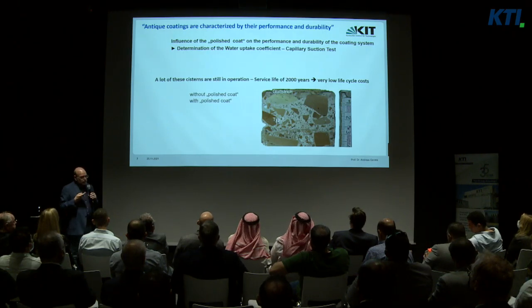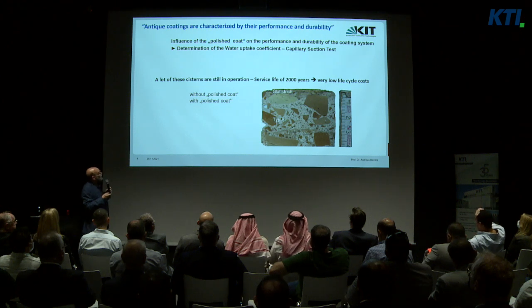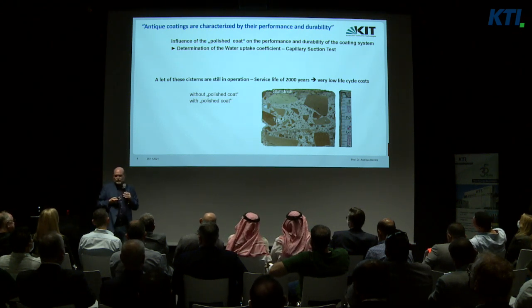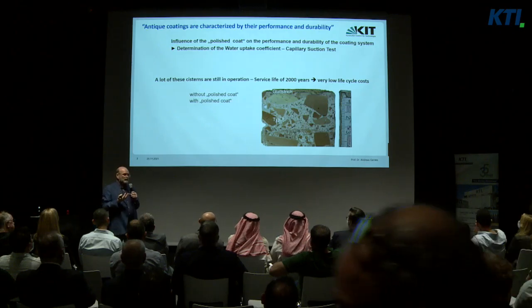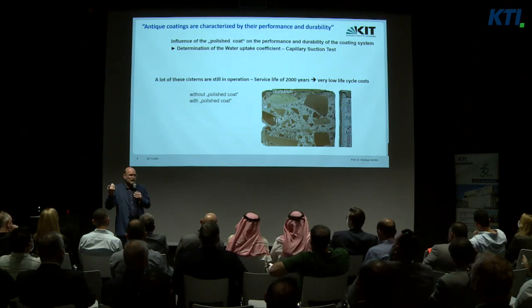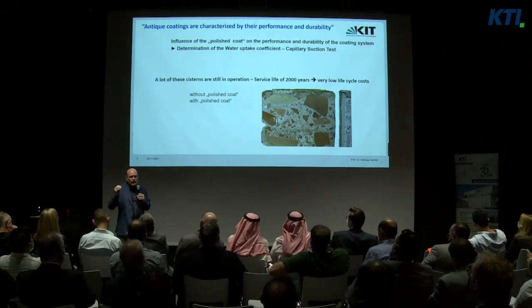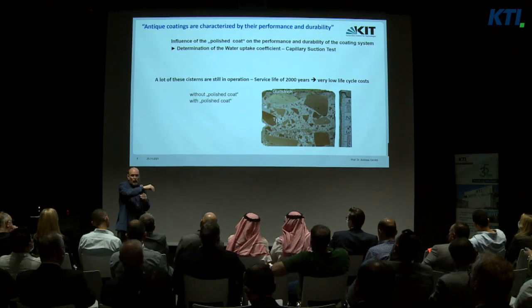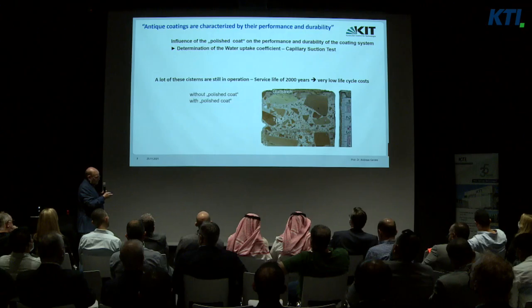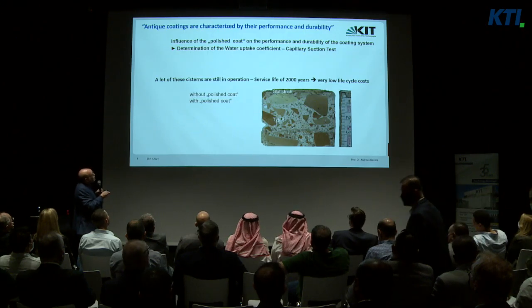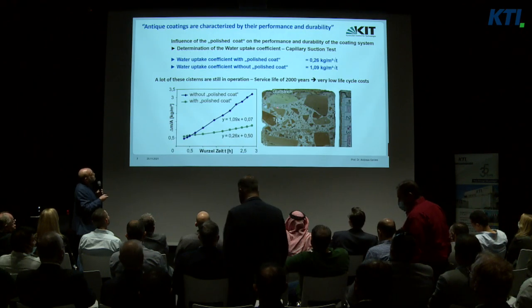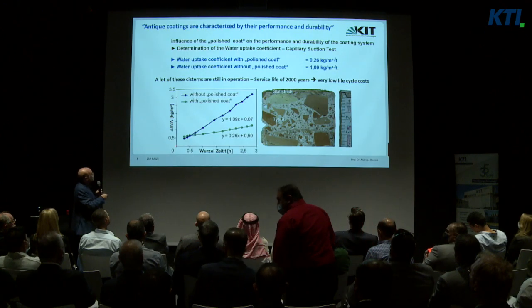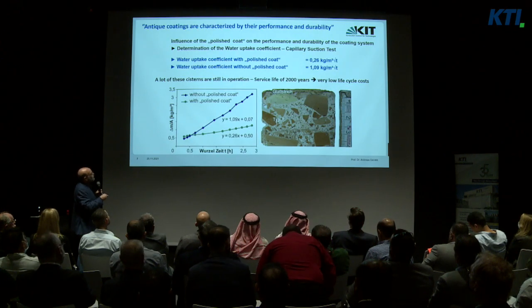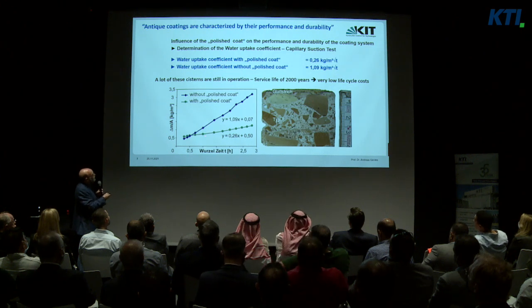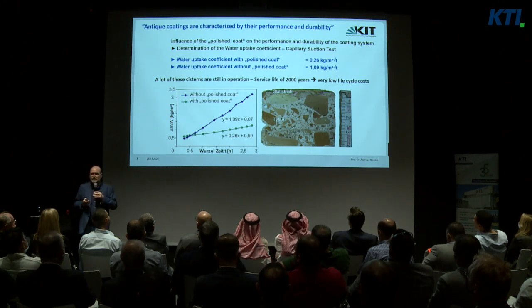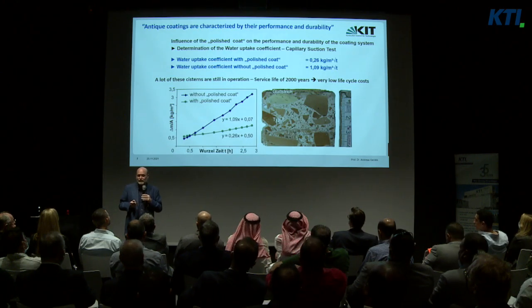And we have tested the performance of this material. We have measured the water uptake coefficient, because you know if a material is porous, then easily materials can go out. They migrate from the mortar into the drinking water, or vice versa, and that will lead finally to a leaching which reduces the service life. And therefore we have tested the water uptake of the porous material, blue colored, so it's a high water uptake, but this polished coat has a low uptake. And this is the solution, that's the reason for the high durability.